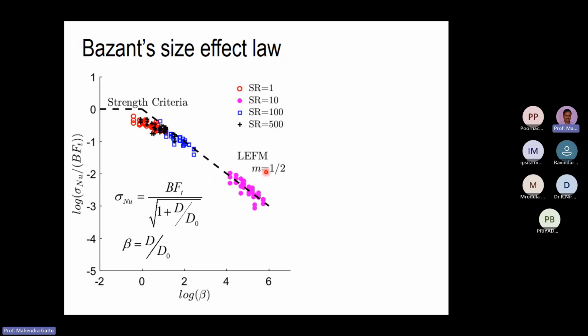And we plotted the size effect law here, which is sigma_N = Bf_t / (1 + sqrt(D/D_0)). So again, the strength criteria we are plotting here, and the LEFM criteria is here. All the experimental data are shown here for 180 test specimens. So you can see for loading rate of 1, the cluster data is close to the strength criteria.